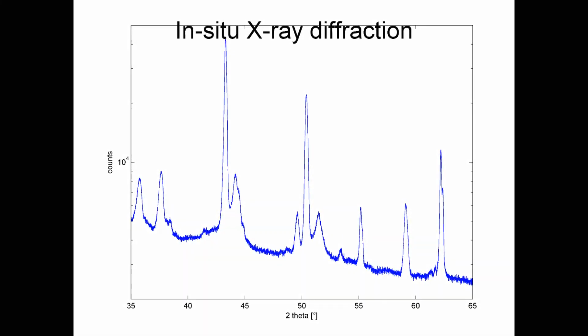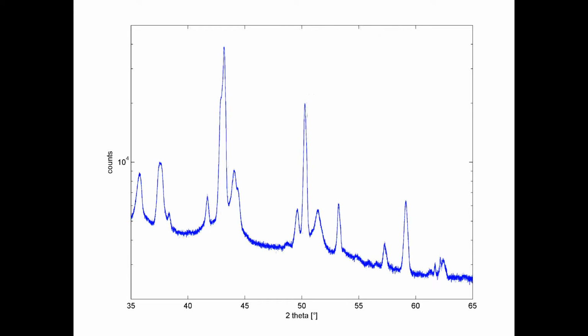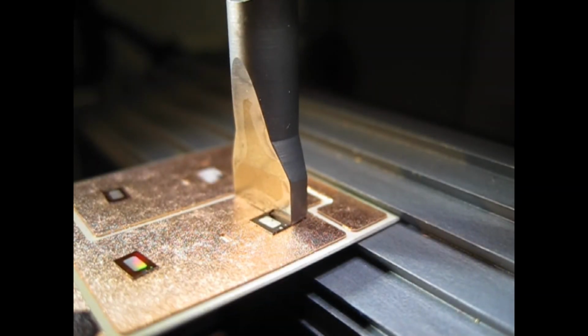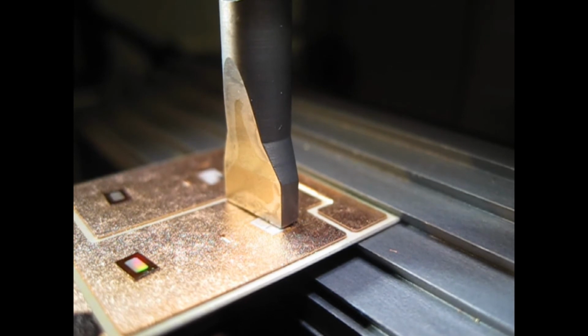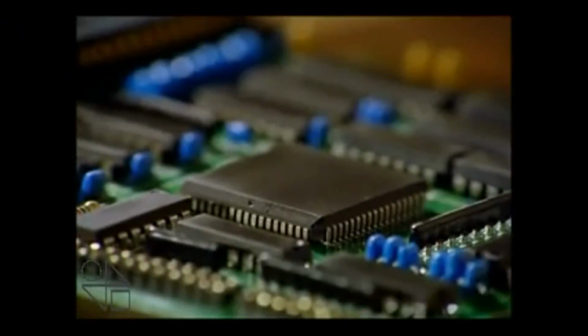This intermetallic compound formation can be followed by focused ion beam microscopy and in situ X-ray diffraction. This method allows it to follow the development of the different intermetallics in real time. Scanning acoustic microscopy can be used to detect voids in the solder joint. And shear test yields information on the physical stability. The goal of my thesis work is to find an interconnect method that can push the limits of device performance.